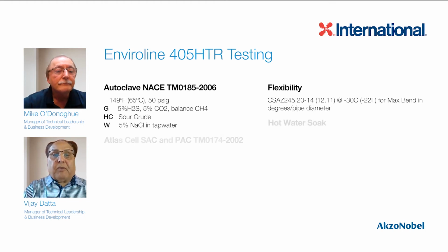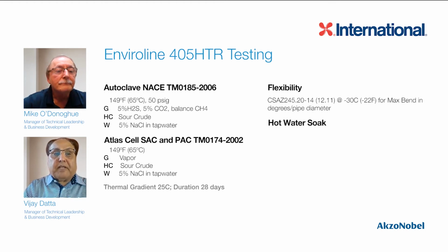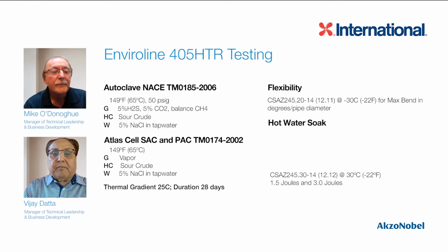Now, let's move into the testing, because like we mentioned before, all coatings are not tested equal. We do a lot of testing for Enviroline 405 HTR. We run the autoclave test at various temperatures with the gas phase, water phase, and the hydrocarbon phase. In this case, you can see here there's a 5% H2S, 5% CO2. The balance is methane.